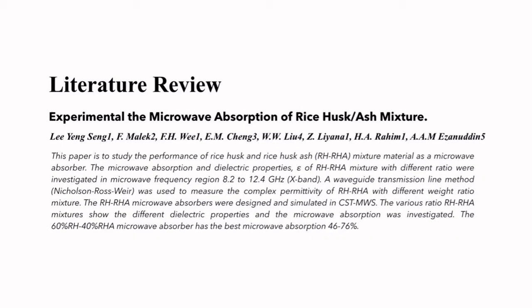Other than that, this paper, titled Experimental the Microwave Absorption of Rice Husk and Rice Husk Ash Mixture, presents the different microwave absorption for different ratios of mixture of rice husk and rice husk ash. The results show that the best ratio for rice husk and rice husk ash admixture is 3 to 2, which absorbs from 46 to 76 absorption.